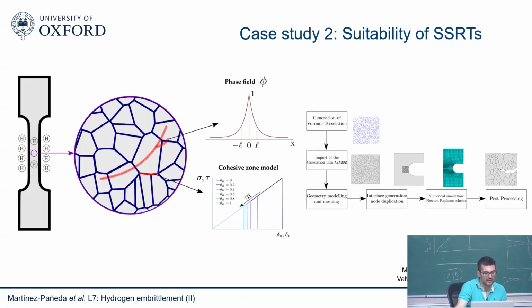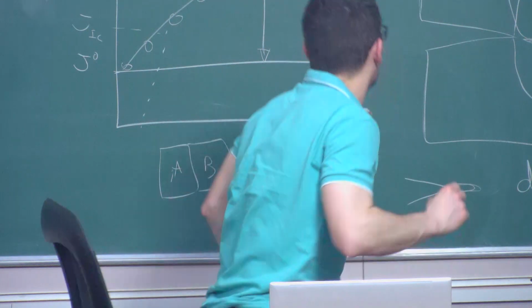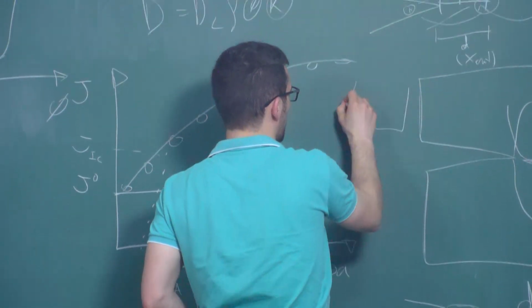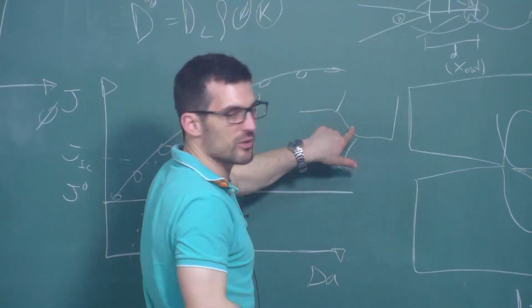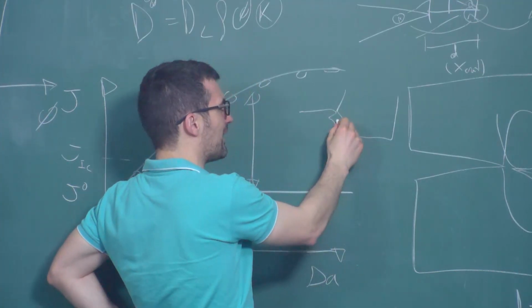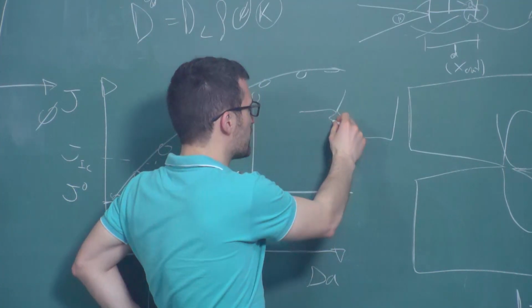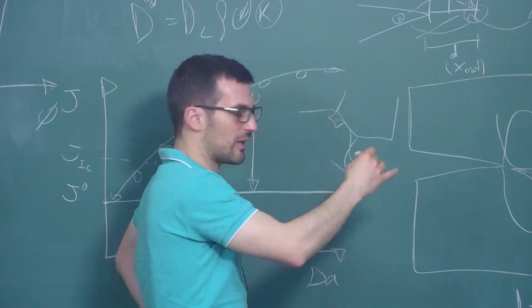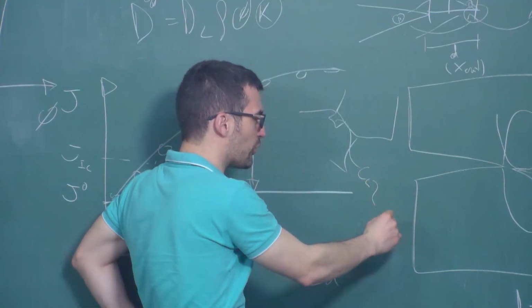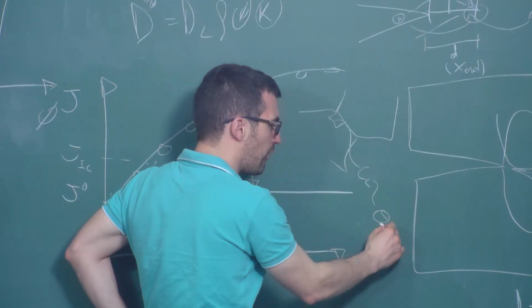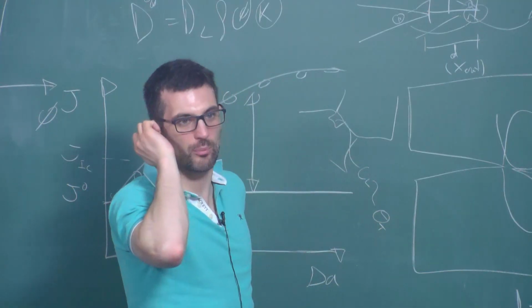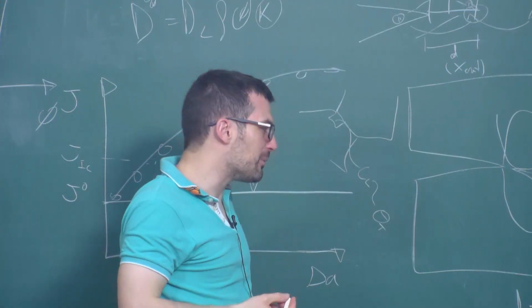So there's two ways of doing it, and now that we're doing a lot of crystal plasticity, we have various ways of doing it. Now you're resolving the grains. The way people did it at the beginning, if you think of a grain here and then another grain there, you are solving this with continuum bulk elements. So you see which is my bulk element closer to my interface. And then you say, okay, if this is my bulk element, and it has this concentration of lattice hydrogen, I can use Oriani's equilibrium to tell me what is the occupancy of a trap with a given binding energy. That's one approach. The way we do it now is a bit different.